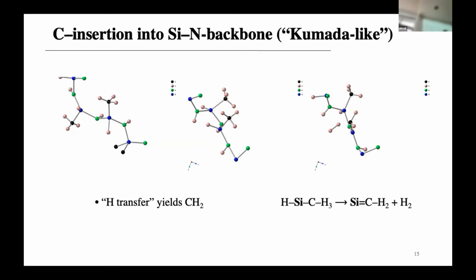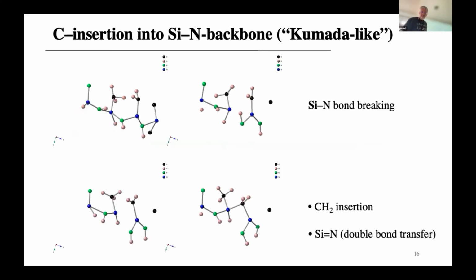However, this is a dominant intermediate situation that is actually relatively long-living in the simulations that happen at 2000 or 2100 Kelvin, for up to half a nanosecond.